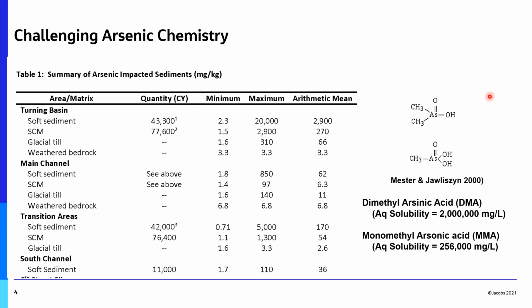So chemically speaking, the two main active agents in the Agent Blue were dimethyl arsinic acid and monomethyl arsonic acid. And the solubilities of these were 2 million milligrams per liter in the case of DMA, and in MMA, it was 256,000 milligrams per liter. So I ask you, what are you going to do here when your TCLP limit is 5, right? These are enormous numbers. So it was a significant technical challenge to devise a method to get below 5.